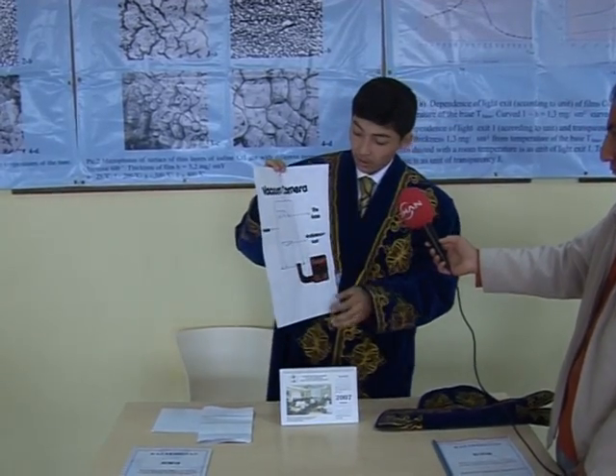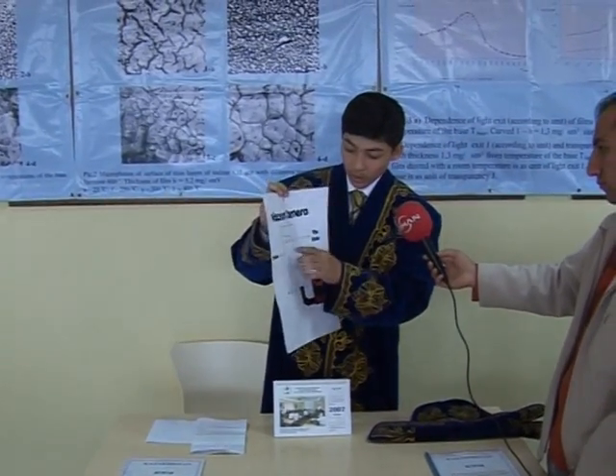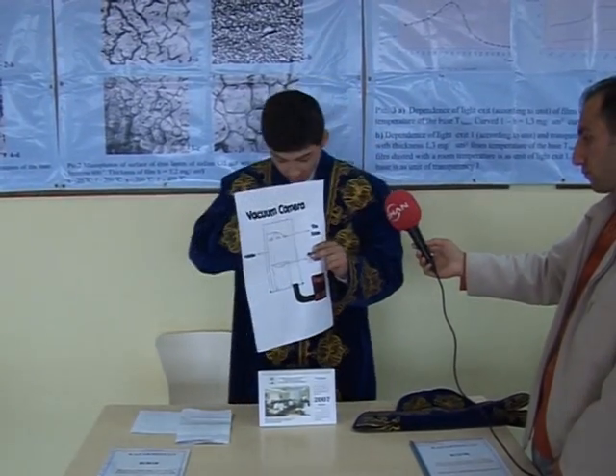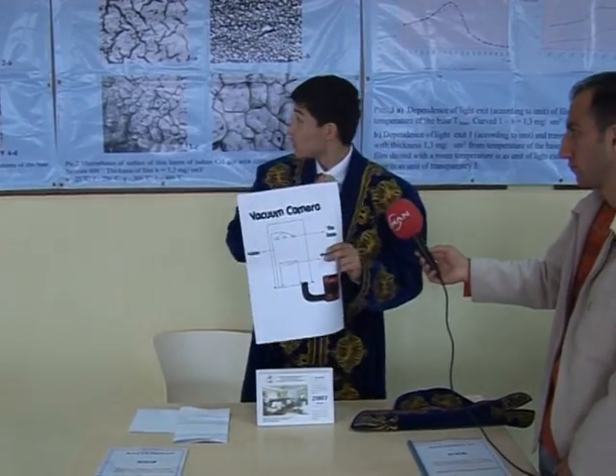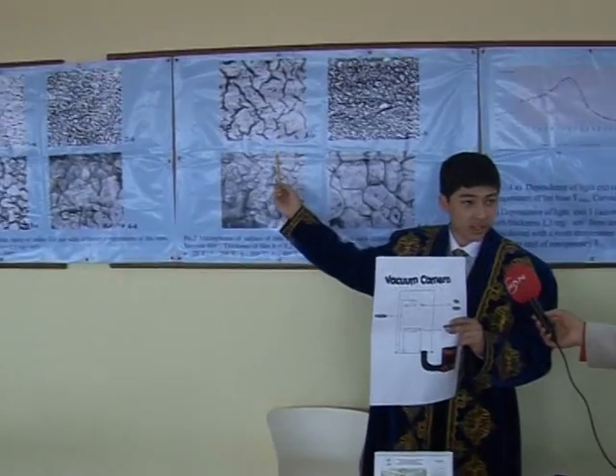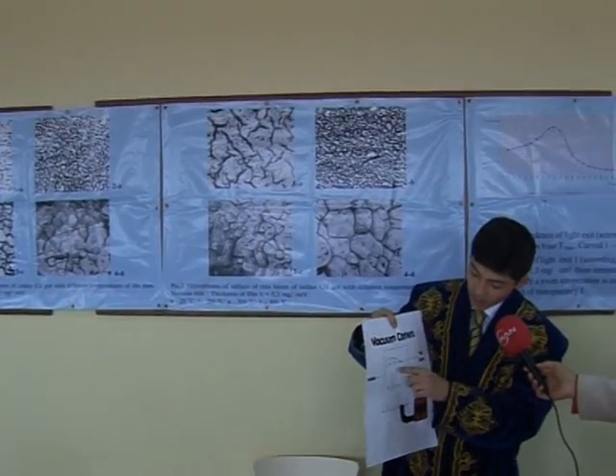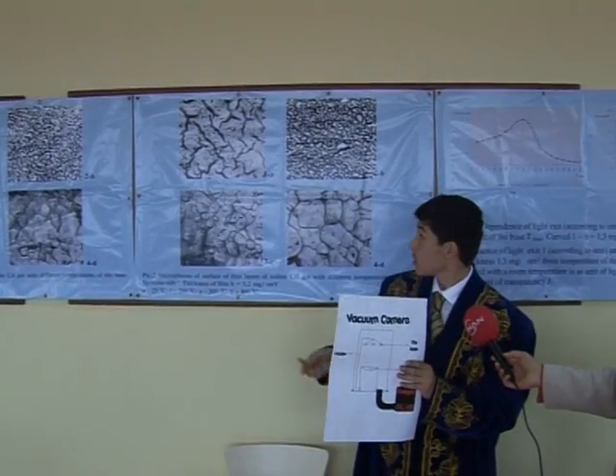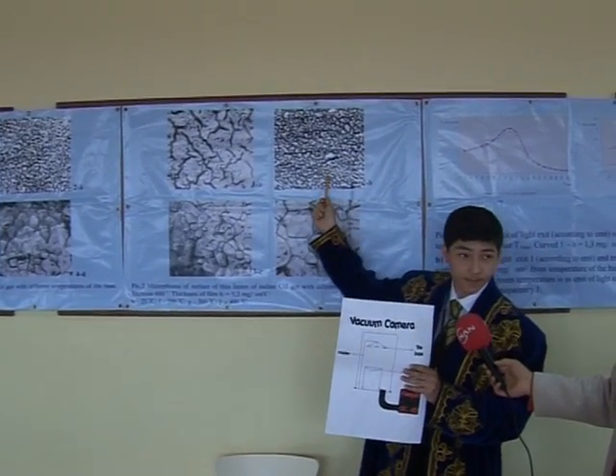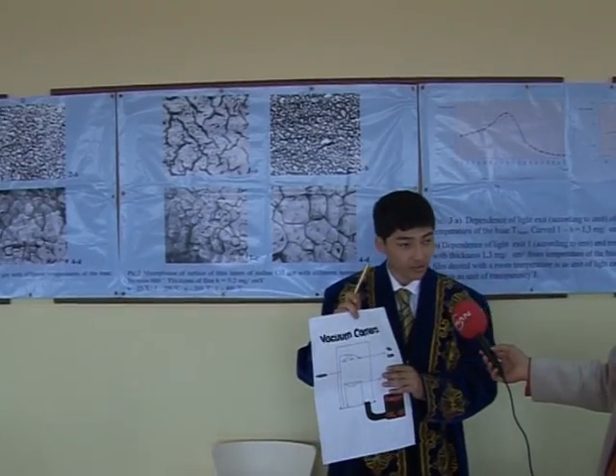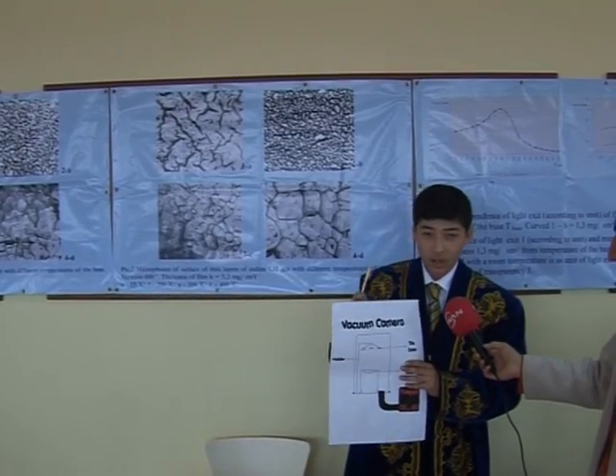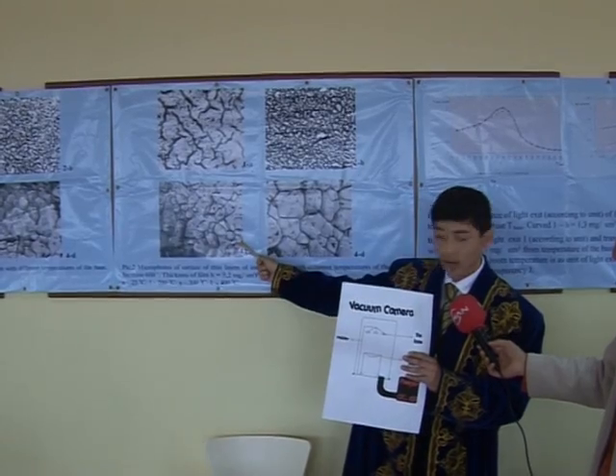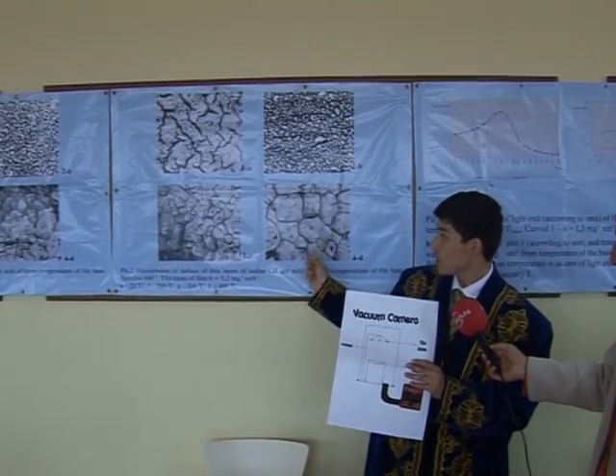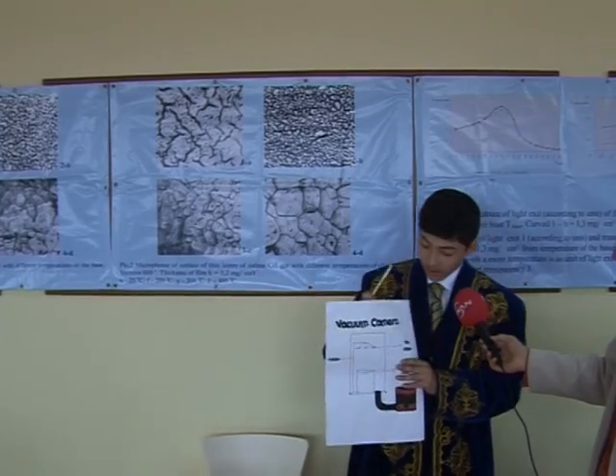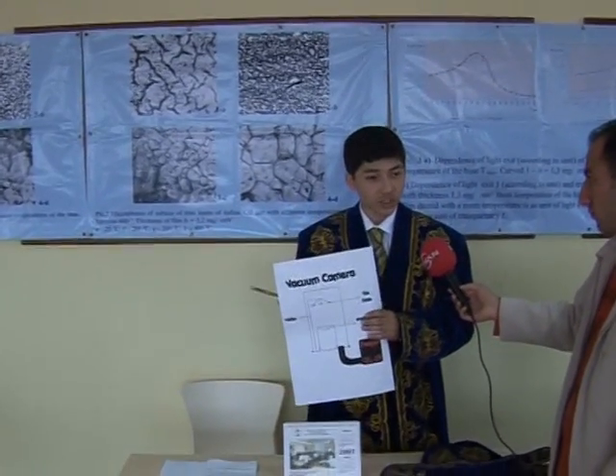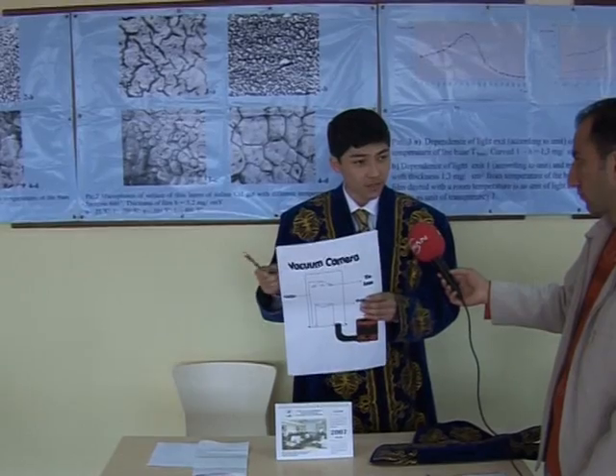If the temperature of the base is 25 Celsius, the structure will be like this: very small crystals. If the temperature of the base is 200 Celsius, it will have a small crystal structure like this. The size of small crystals increases with the increase of the temperature, at 300, at 400. As you see, they are very big. The size of small crystals also increases with the increase of the thickness.